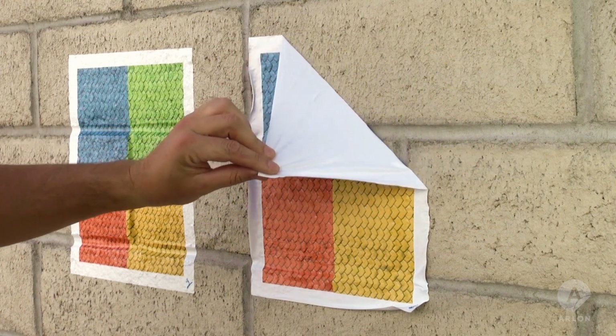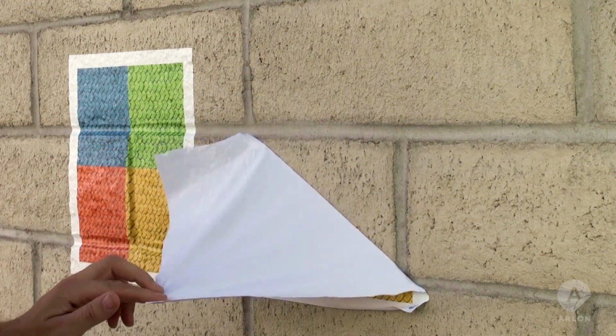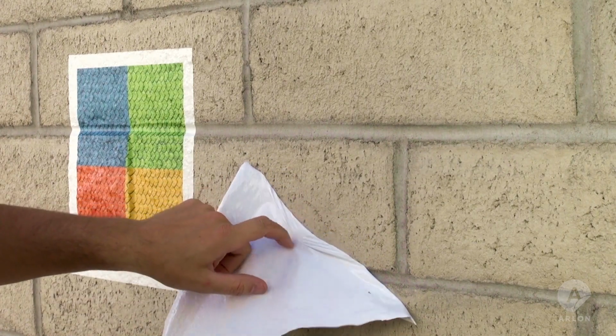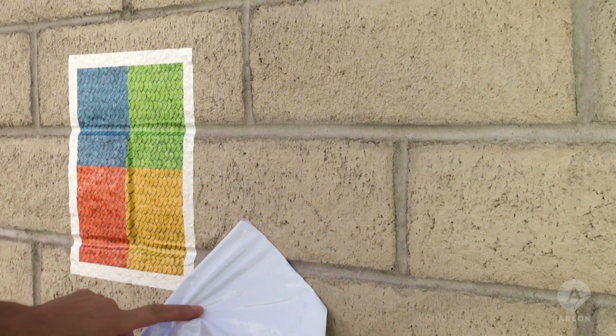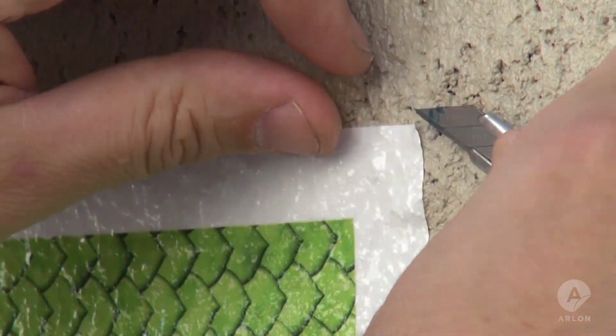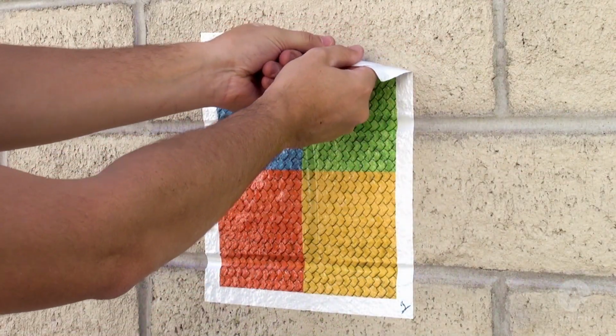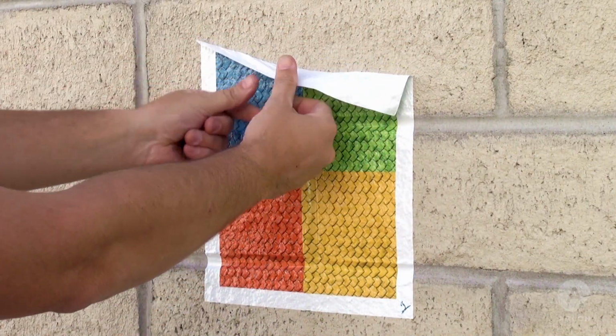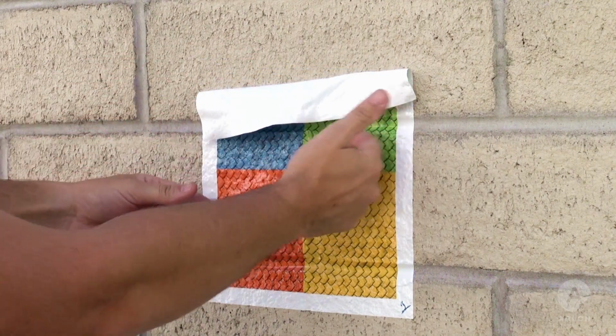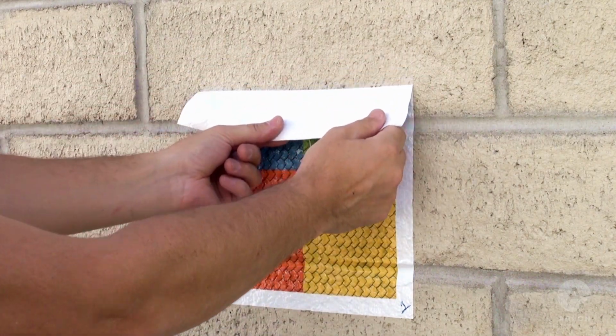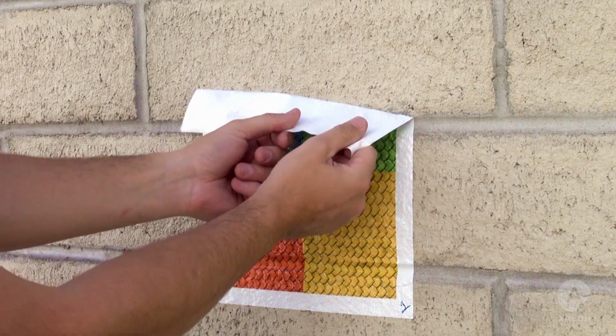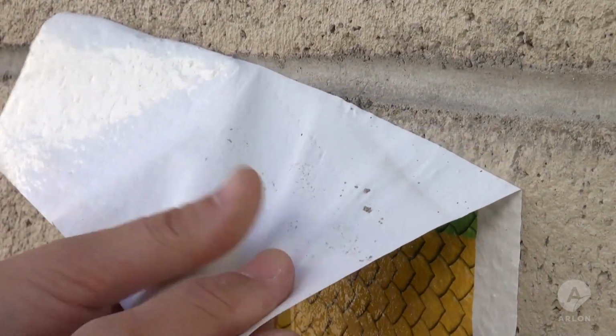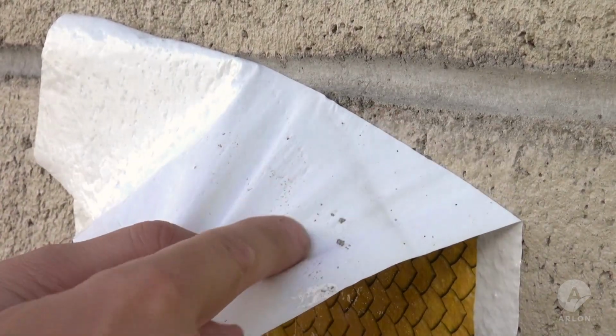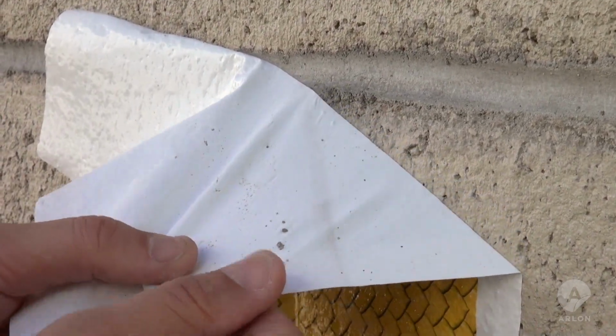Next, test the adhesion value of the vinyl to the wall surface. Again, sample number 2 is obviously not compatible with this wall texture. Sample number 1 has bonded well. You can see how the adhesive is cured into the porous aggregate surface. You can see how much tension I have to apply to remove the vinyl, and some small particles may come with it.